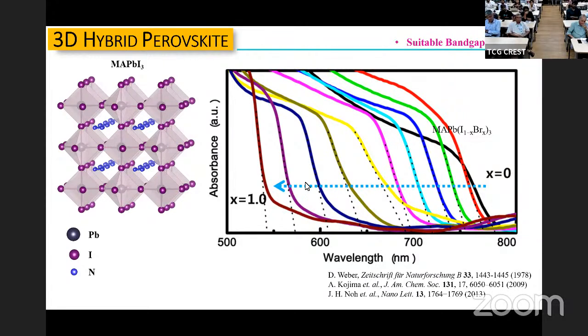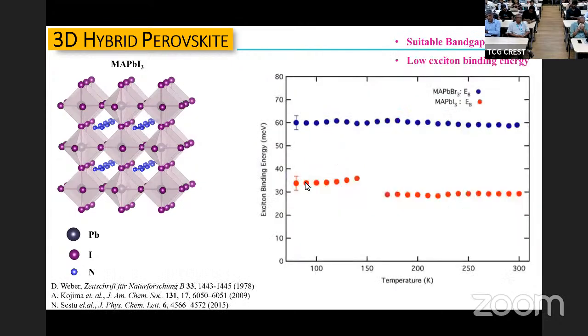And people are making light-emitting diodes from these materials, and it's believed that it might yield some very interesting results. So suitable band gap is an exciting aspect of it, and the fact that you can engineer the band gap for the purpose that you have in mind. It has very low excitonic binding energy. I told you why we need low excitonic binding energy. If the binding energy would be too large, then you cannot separate the electron and hole, and then it will not drive the current outside.